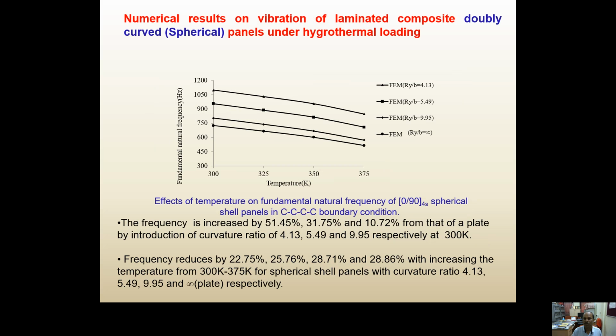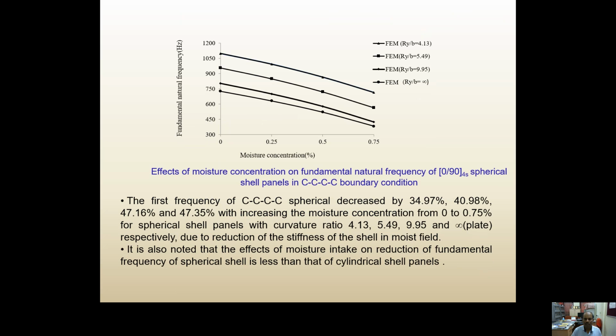Some numerical studies are also carried out for doubly curved shell panels under hygrothermal loading. So this is a spherical shell panel subjected to fully clamped boundary condition for different curvatures. The frequencies are significantly increasing with respect to the cylindrical panels, but they decrease with increase of temperature. The effect of moisture concentration on the frequency of spherical shell panels subjected to clamped boundary conditions: the frequencies decrease with increase of moisture concentration.